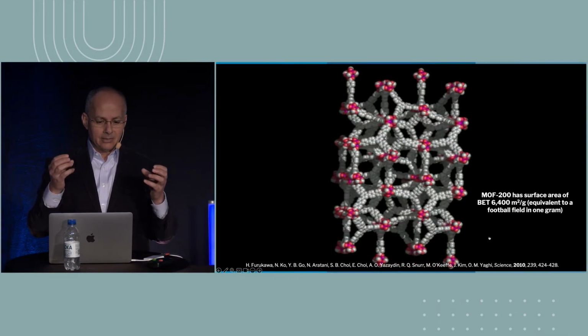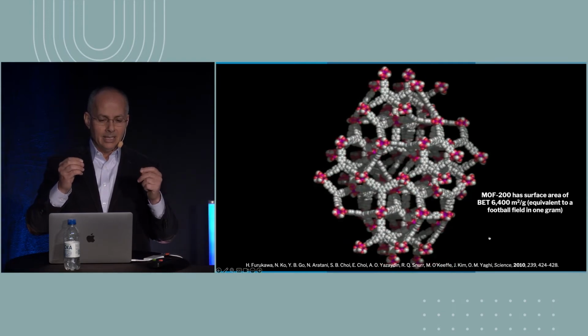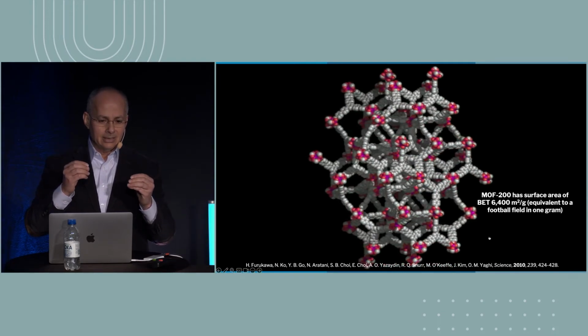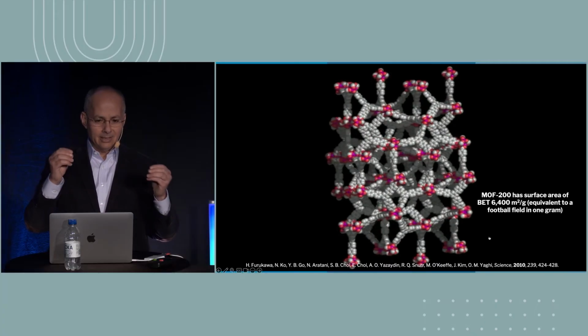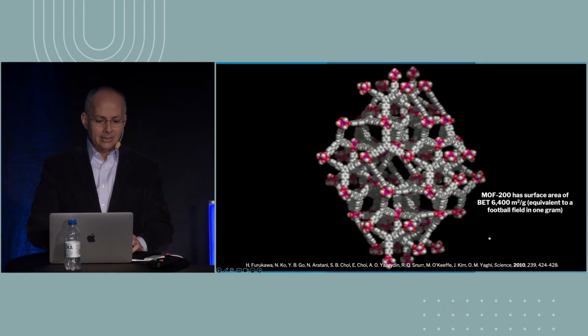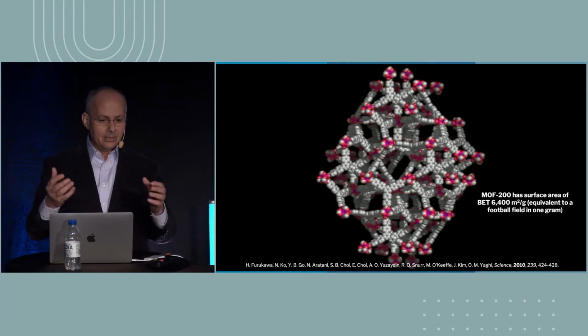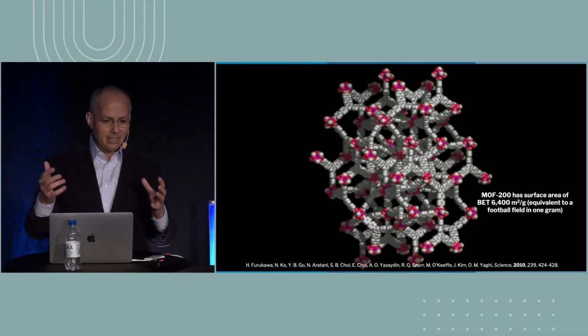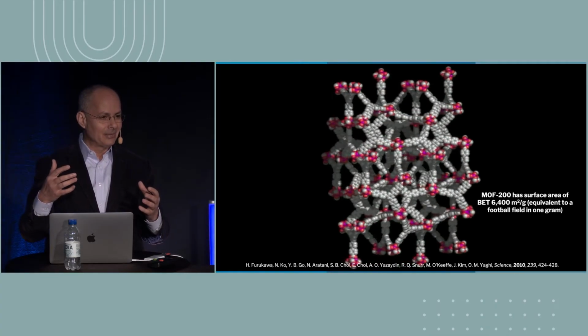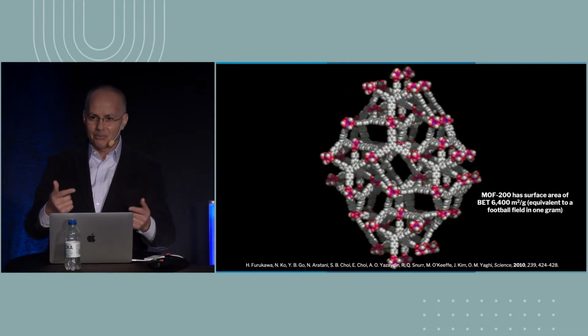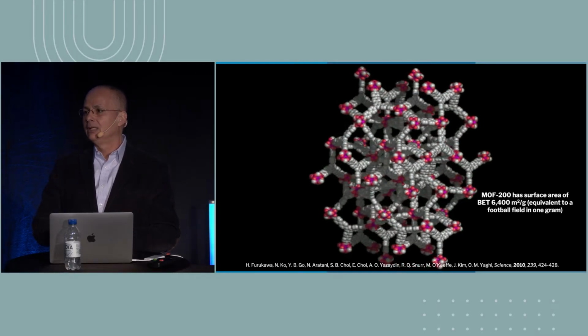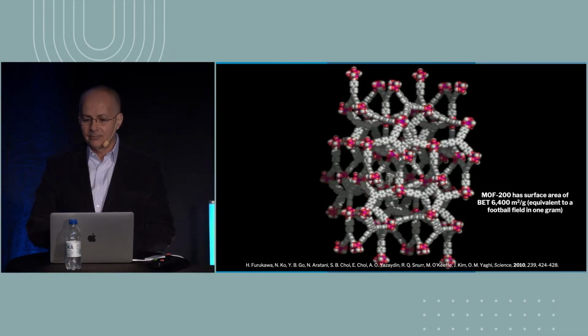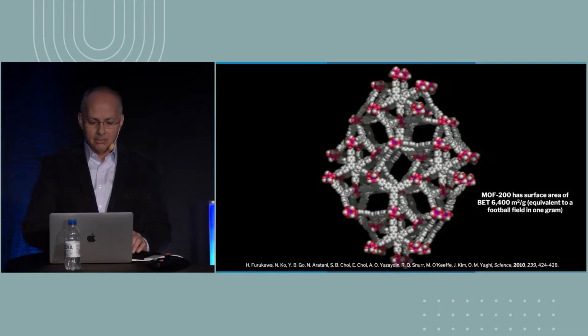So you've got your metal oxide units in pink, and they are linked. Now notice that I've used a trigonal linker that has many exposed faces and edges. And notice that this is a porous material, but the pores have no walls. It's a scaffolding, designed to expose maximally the atoms in the structure. And that's why they have extremely high surface area.